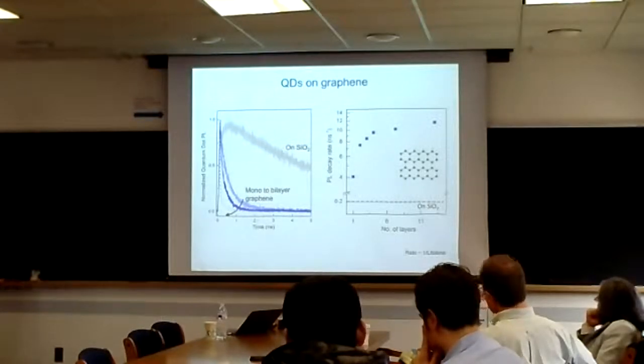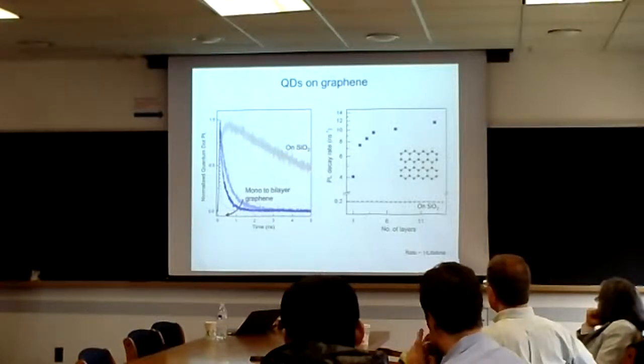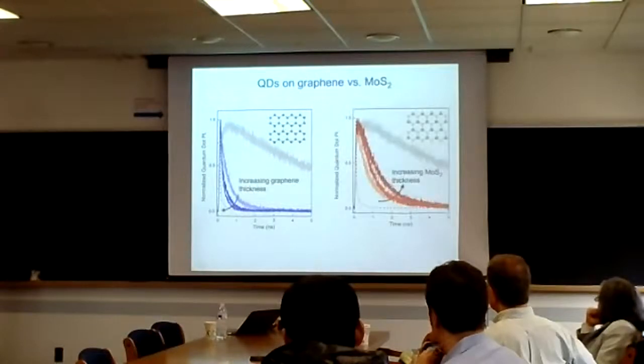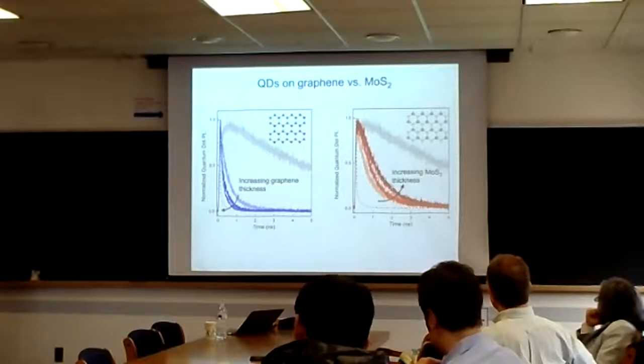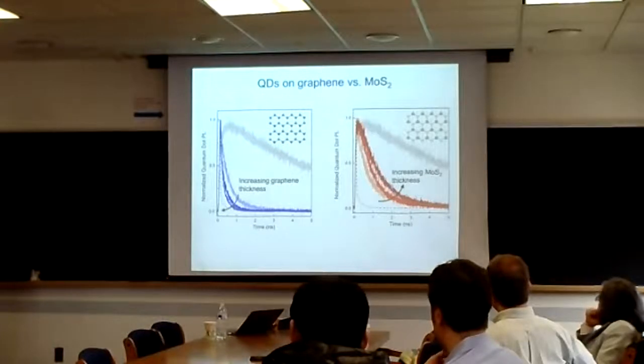And the more graphene layers, the more efficient this decay rate, this energy transfer rate into the material, and that seems reasonable. However, when we did this exact same experiment on MoS2, we observed the opposite. If you start with a monolayer of MoS2 and add one more layer, the non-radiative energy transfer rate goes down by an order of magnitude, and starts decreasing.